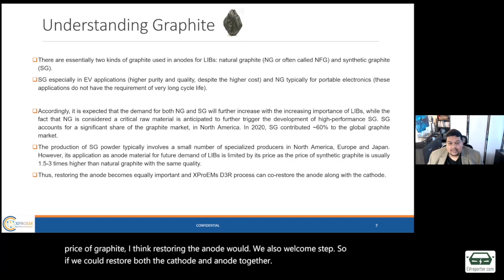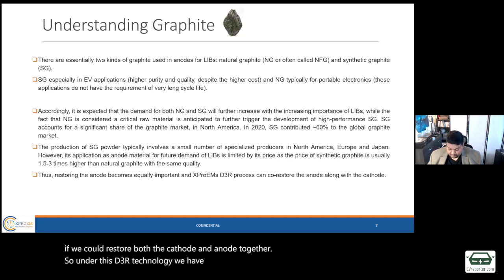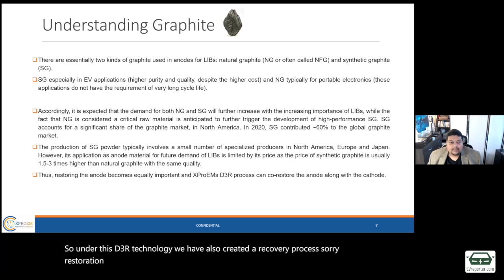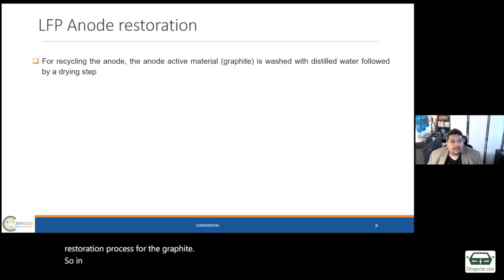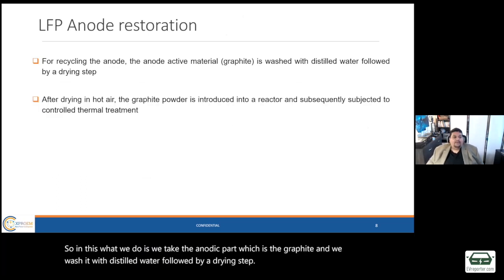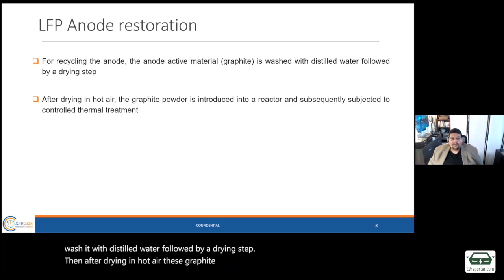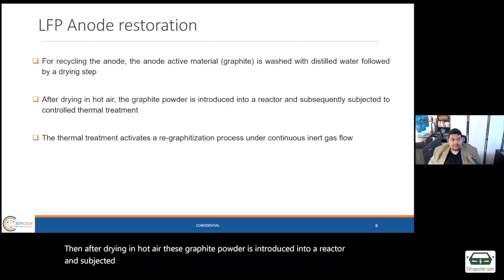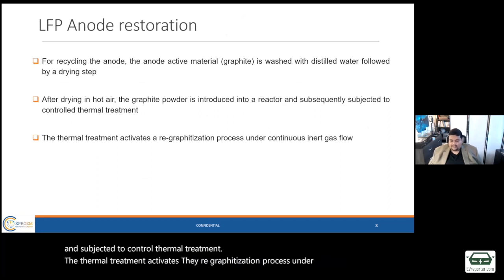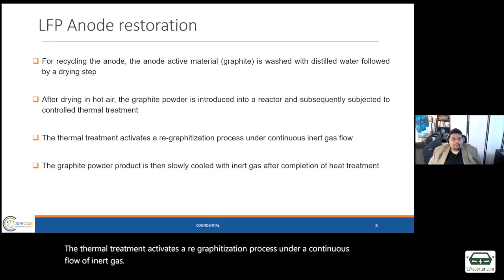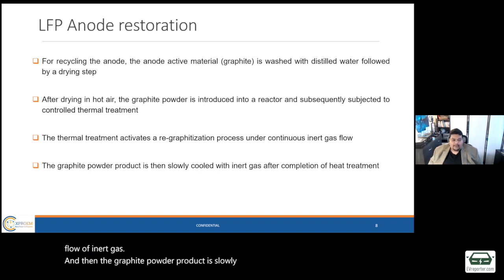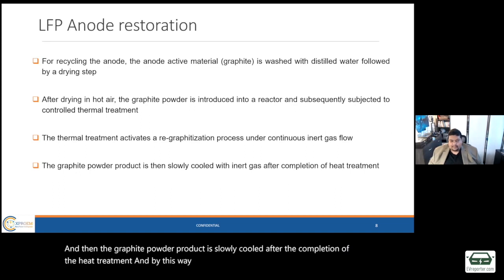Under this D3R technology, we have also created a restoration process for the graphite. In this, we take the anodic part, which is the graphite, and we wash it with distilled water, followed by a drying step. Then after drying in hot air, this graphite powder is introduced into a reactor and subjected to controlled thermal treatment. The thermal treatment activates a regraphitization process under a continuous flow of inert gas. And then the graphite powder product is slowly cooled after the completion of the heat treatment. In this way, with this regraphitization process, we are also able to recover the anode.